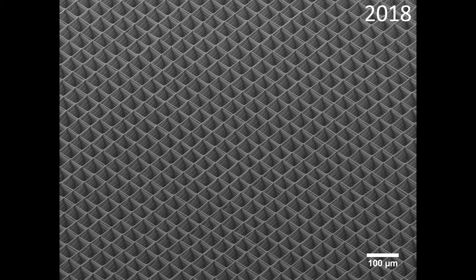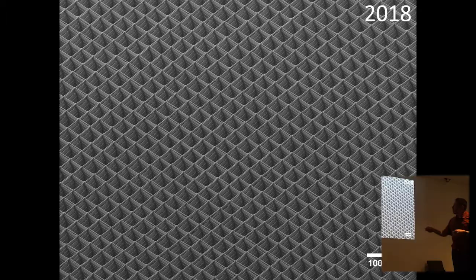So this is a SEM image of a 50 micron box scaffold that we made in Würzburg. Martin Yusuf has made this, and this is really pushing the limits of the technology. We have fibres that are quite close together and also have quite a few layers, and so this is really the limit of making these perfect scaffolds. That was, I think, this summer.